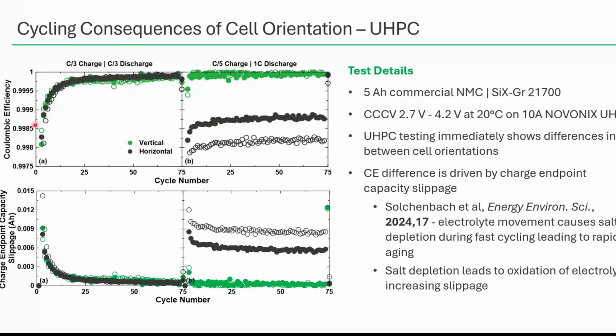We've got nearly identical coulombic efficiency with C/3 between vertical and horizontally oriented cells. But at C/5 and 1C, we see actually very poor performance in these horizontal cells, and fairly inconsistent results. This is a bit of a red flag - something's going on very early, almost in the first couple cycles, within hours or a day of starting this test, and we can see this big difference.